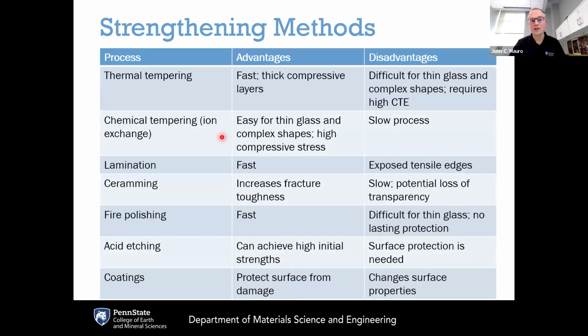How do we actually do that? One common way is thermal tempering. Thermal tempering is where you take thick, flat pieces of glass, subject it to a fast cooling where you can freeze in the exterior surfaces of the glass faster than the interior part of the glass. This pulls the exterior into compression. This has the advantage that it's fast. You get really thick compressive stress layers, but you really can't do this with thin glass, and you can't do it with complex shapes, and it also requires glass with a high thermal expansion coefficient, like soda-lime silicate glass.